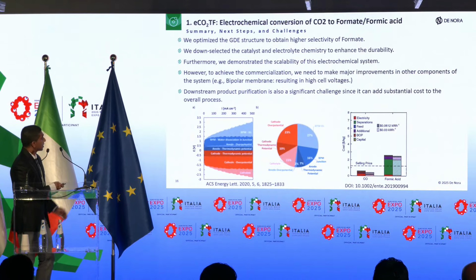With that, I would like to wrap up this part of the presentation. To summarize, we optimized the GDE structure to obtain higher selectivity for formate, and we down selected the catalyst and electrolyte chemistry to enhance the durability. Also, we demonstrated the scalability of the electrochemical system. However, there are two main things I want to highlight. To achieve commercialization, we realized we need to make major improvements in the other components, such as the bipolar membrane.